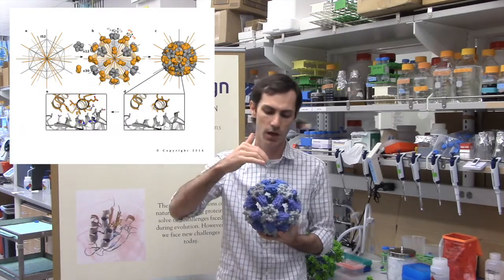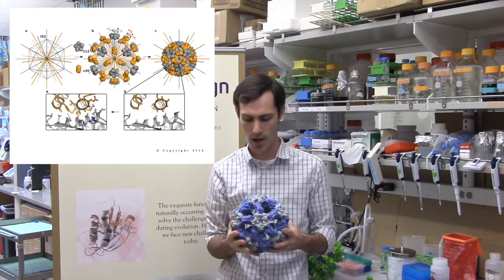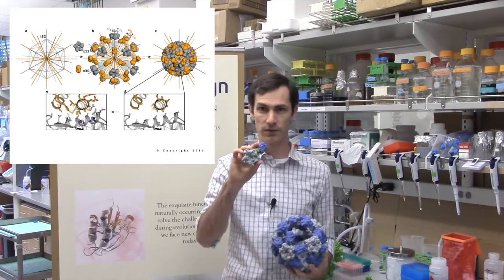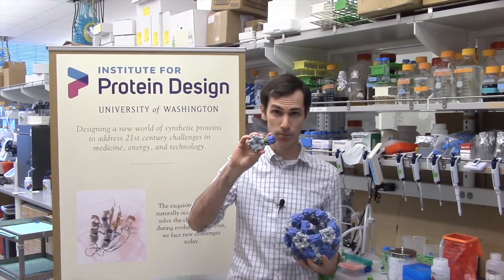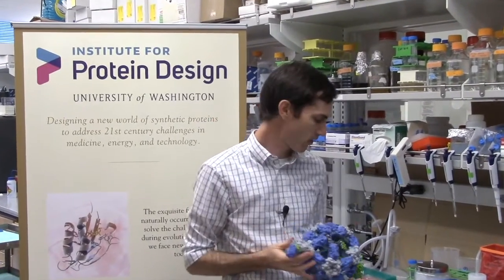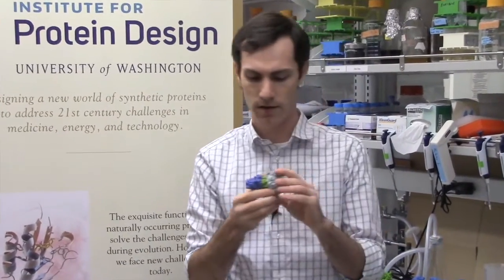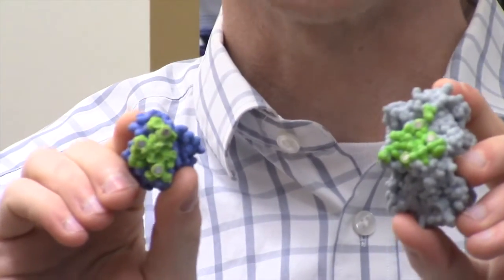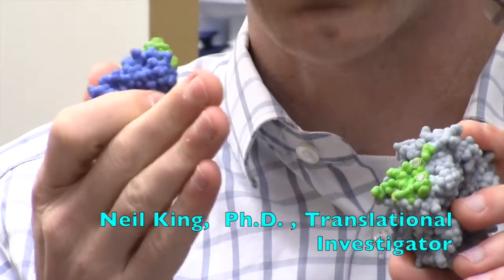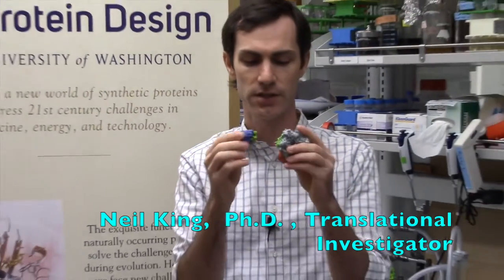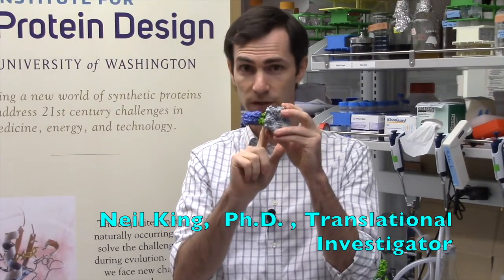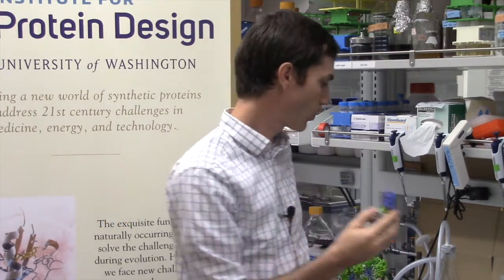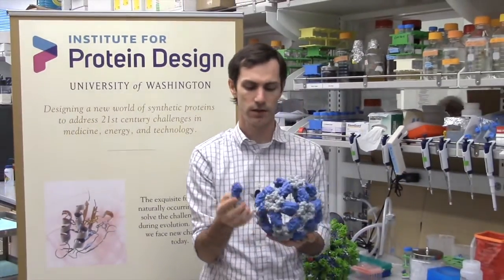So this is an example of what we call a two-component assembly, where you have a gray protein and a blue protein that co-assemble to this architecture. You can pull out two building blocks, one dimeric blue protein building block and one pentameric gray protein building block, and then you can also break those apart, and you can see in green the designed interface highlighted. So this was the portion of the protein surface where we used the Rosetta software to introduce mutations that would stabilize this particular geometry between these two protein building blocks, which when repeated symmetrically leads to this icosahedral nanomaterial.